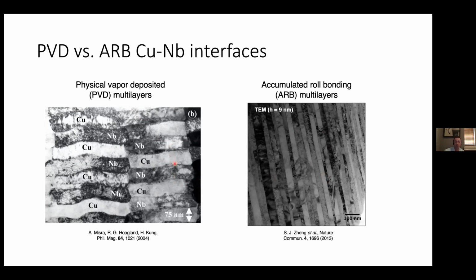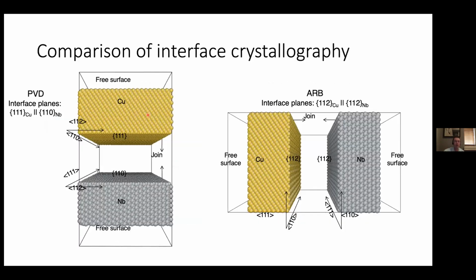In particular, for the ones on the left, the physical vapor deposited ones, we can describe the interfaces as forming along closest packed planes. So if you look at the copper layers, the interface plane is the 111 type plane. The niobium layers, the interface plane is the 110 type plane. And if you join those two planes together, you'll get the interface of the type that we see in the